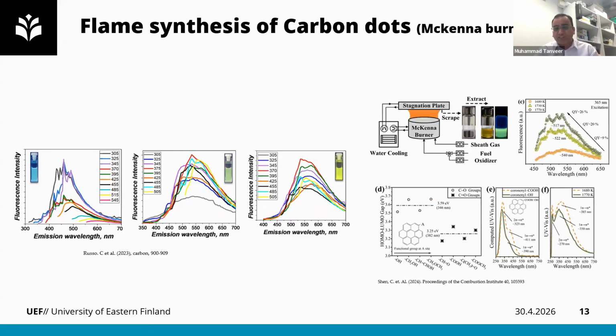In the next study, they have shown that temperature is also playing a quite prominent role in the quantum yield and also in the fluorescence of carbon dots. As they increase the temperature, like you can see here, the quantum yield and the fluorescence will increase. And they also showed that the HOMO-LUMO gap, I mean the band gap, you can say, for the molecules, is affected by the different functional groups and also the polyaromatic hydrocarbons. So as the sizes of these PAHs increase, or the nature of functional group on the surface of carbon dot is changed, the HOMO-LUMO gap will change, and it will actually give a different kind of photoluminescence. So by tuning these parameters, the application of carbon dots can be changed and they can be applied in different areas.